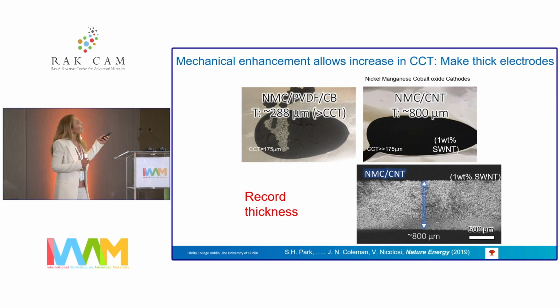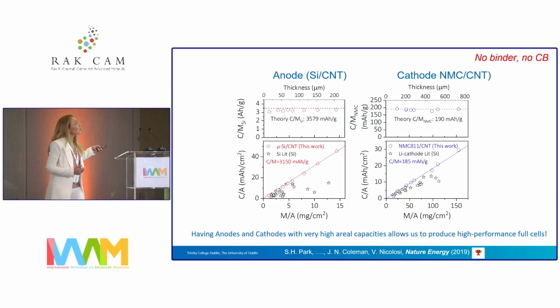And this is perhaps the most striking achievement in this case. If you look at the conventional way of making electrodes with carbon black and a polymeric binder, the three-element system that we discussed before, you actually reach the critical crack thickness of the electrode already at about 280 microns. While with our method of the segregated networks, you go up to and above 800 microns. So the more thickness, the more material, the higher is what you can store. And this is really what we achieved.